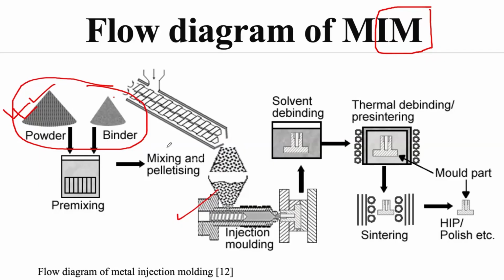And the metal powder does not change its phase. Rather, it keeps on being embedded within the particular structure. Once it has been injection molded, you will get the shape of that structure. Now, because you want a fully fabricated metal part, you have to remove all these things that you are adding into the recipe together with the stainless steel powder. If you're adding thermoplastic elastomer, that needs to go. If you are adding surfactant, if you are adding binder, all these things need to go.